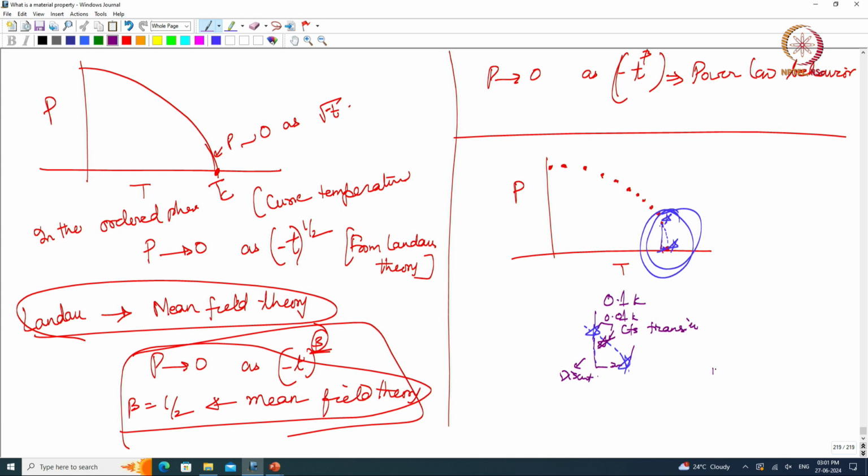In any case, there is some data sampling that you do, and temperature has a minimum temperature step. So, whatever the temperature step, I will always find myself in the situation where, between the last two data points, I am not sure if I have a continuous transition or a discontinuous transition in some sense. So, these are the sort of issues that come when I have to see whether it is a second order phase transition or a first order phase transition.